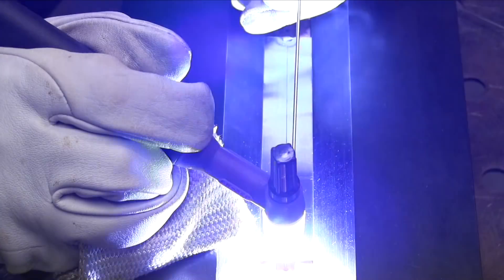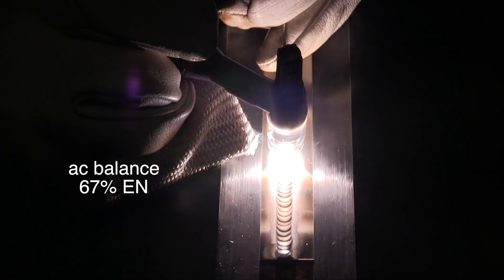I'm using a number eight clear cup here. And you can watch me light up on this tack just like you did on the stainless. And it gives me an extra, like I said, an extra half a second or so to prevent from melting that end away. And the technique works on pretty much every metal that I've ever welded. Definitely not the only way to do it, but it works. Now, for passing a test like this on aluminum, I have found that having my AC balance setting with quite a bit of cleaning helps in passing x-ray. And also, I don't typically use the higher frequencies. This is set at 77 hertz, which is just slightly higher than what you can get out of a transformer type machine. But all I'm saying is that's what worked. That's what yielded the best results when we had to stop and test things and figure out where porosity was coming from. So I just kind of leaned into those settings.